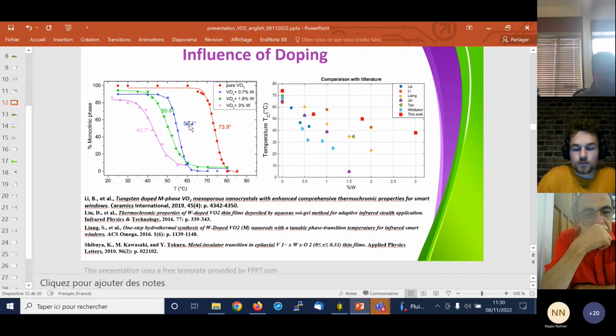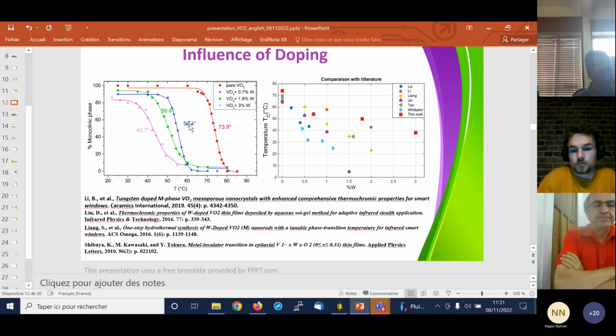In many cases, it depends what type of films you are making. In this case, we were asking for thin films, typically of the order of less than 100 nanometers. Of course, some people are making much thicker films, and then it's very difficult to get the thickness from reflectivity measurements, because then you don't see the fringes, and it's a problem.